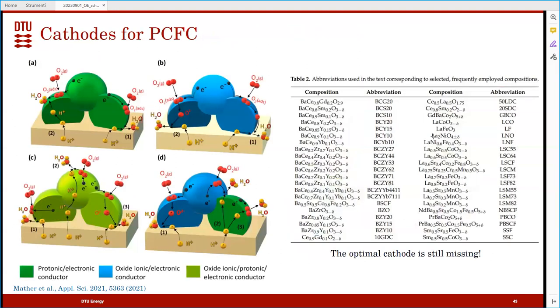And we are looking at this in different ways, using basically high entropy alloys. And the method is even more complicated, because if you're interested in proton conducting fuel cells, this is a great review. You can see here there are a bunch of materials that can do different tricks, but also different ways of doing it, where the reaction can happen on the cathode, on the interface between the cathode and the electrolyte. You could have materials that conduct protons, conduct electrons, conduct oxygen vacancy, can conduct all three, so they use all the surface to run the ORR reaction and so on. So we have so many different parameters we can optimize on this. And of course, we don't want to reduce to the simplest case, because maybe we are just excluding something that is much more interesting or much more futuristic than the rest.